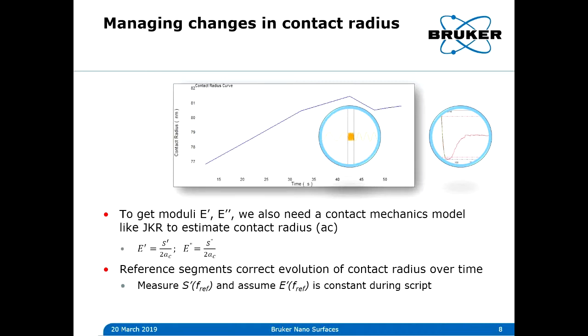Well, okay. So the calibration goes as follows. What we do is we scan the box of probes, and the box already has the information of each cantilever. Essentially, it knows the tip radius of the probe and also the spring constant of the probe. So that's already there. We are missing the deflection sensitivity. So we engage on a hard sample like sapphire, and we do a ramp and find the deflection sensitivity from that. At that point, our system is calibrated for doing force measurements, but there is one additional calibration that's necessary because the system is very sensitive to phase shifts.